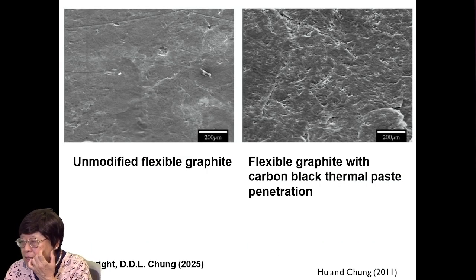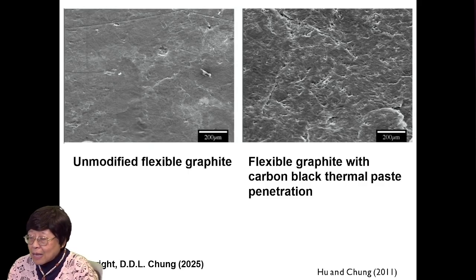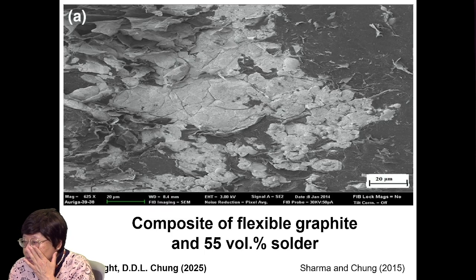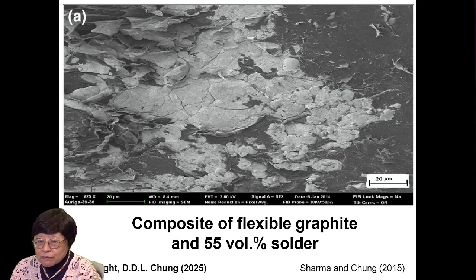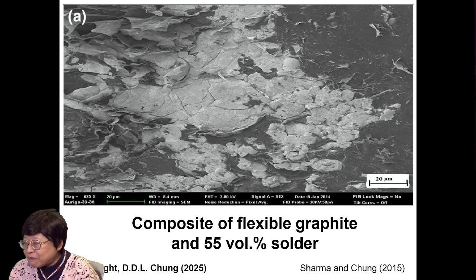Shown here at the left is the unmodified flexible graphite. On the right is flexible graphite with carbon black thermal paste penetrated in the flexible graphite during the making of the flexible graphite. This penetration is not the same as the coating that I mentioned in the last slide. And here is a composite of flexible graphite with solder particles incorporated again inside the flexible graphite. So these are further modifications of flexible graphite.